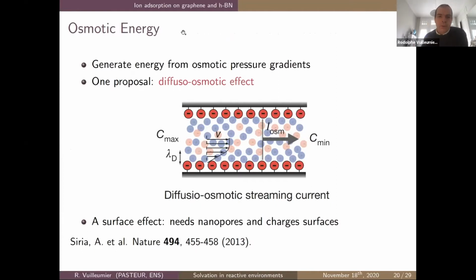That is, when you have salted water and water with a lower concentration of salts, you use the gradient of concentration to produce an electric current. If you have charged surfaces, the difference of concentration induces a difference in Debye length on both sides, which introduces a gradient of pressure in this surface region that then induces a current, and because the system is charged, it induces an electric current that you can try to harvest to get electricity from this gradient of concentration.